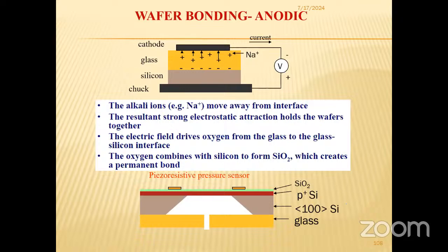Next is anodic bonding. We can see that the orange or yellow colored one is the glass slide, and the lower one is silicon. For this glass and silicon bonding we need some potential, and this electric field makes it possible to bond glass and silicon. The alkali ions, actually Na plus ions, move away from the interface, and after applying this potential, the silicon and glass can be bonded. This is for making rugged structures. To make the structure rugged, we follow silicon glass bonding through anodic bonding technology.